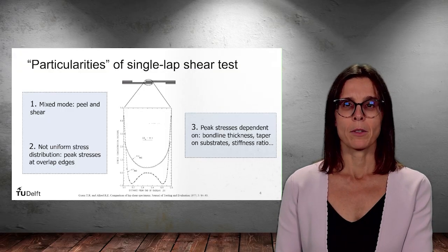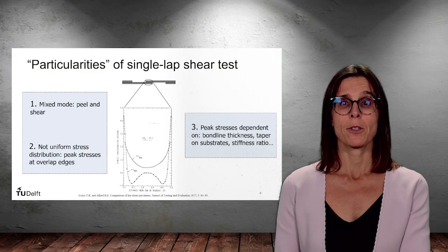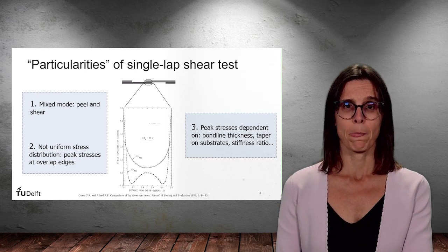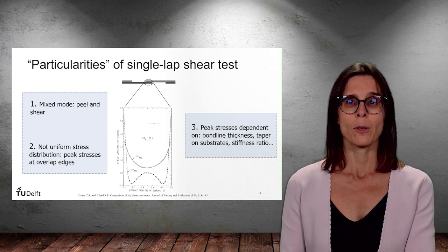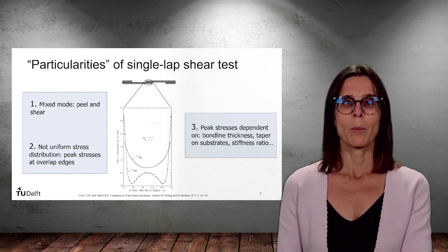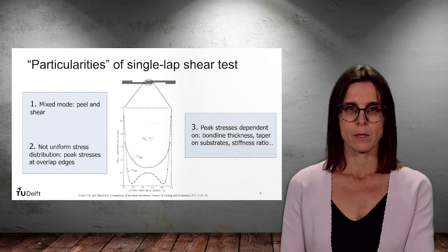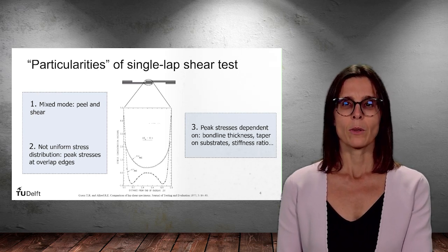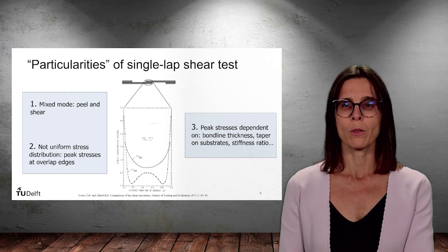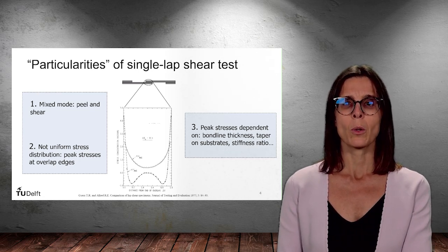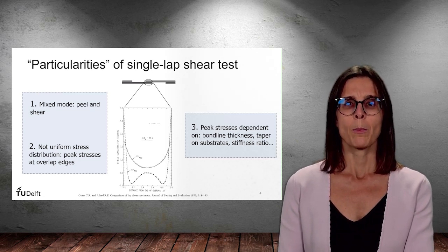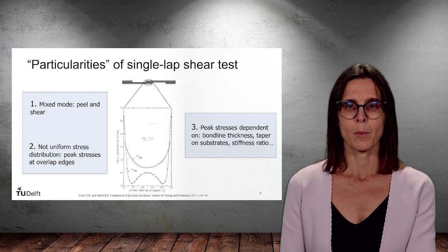We should, however, be aware that the single lap shear test has some particularities. Firstly, the joint is not subjected to pure shear, but to a combination of shear and peel stresses. Secondly, the stress distribution at the joint is not uniform, but it features a so-called bathtub shape, with peak stresses at the edges of the overlap.